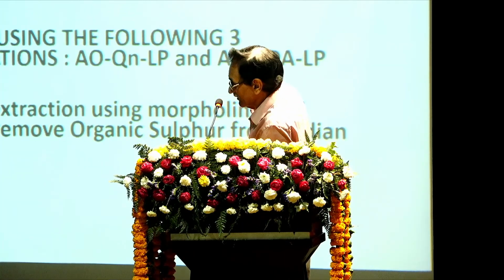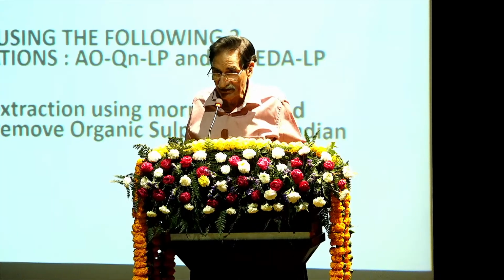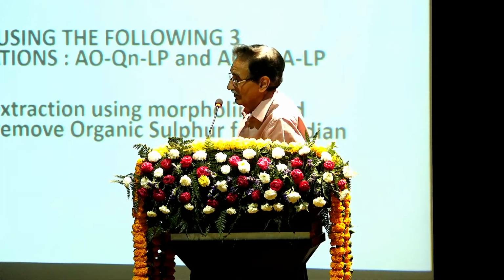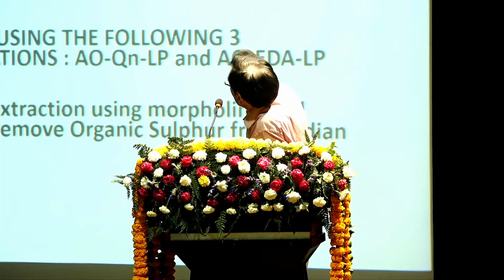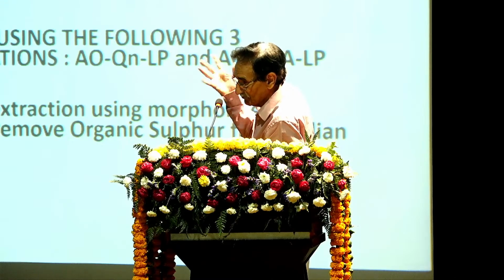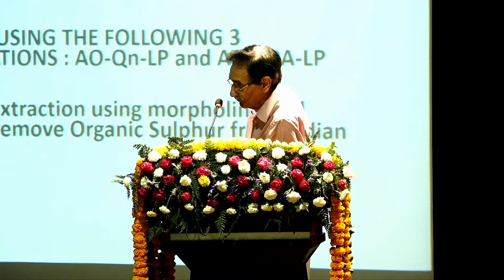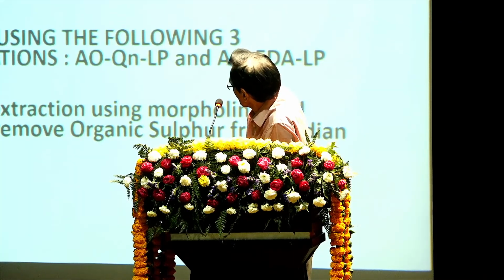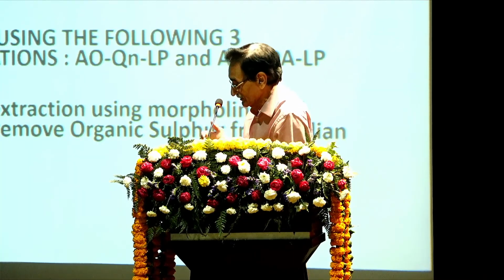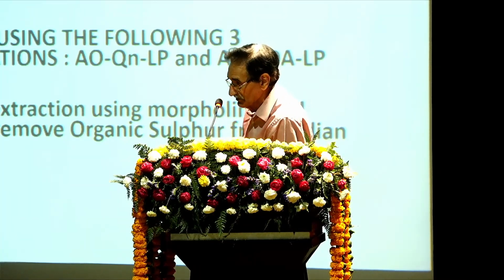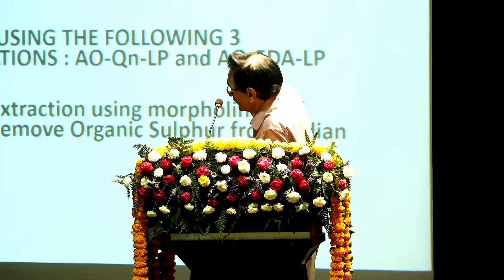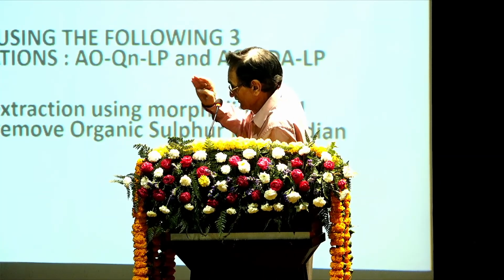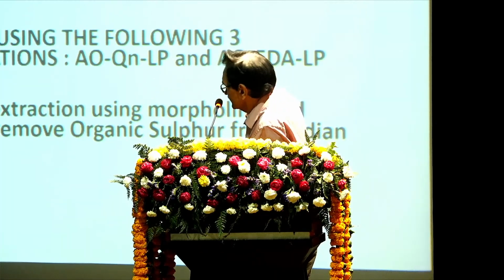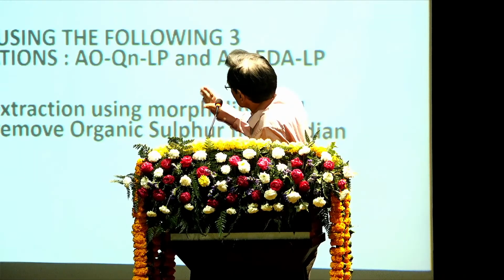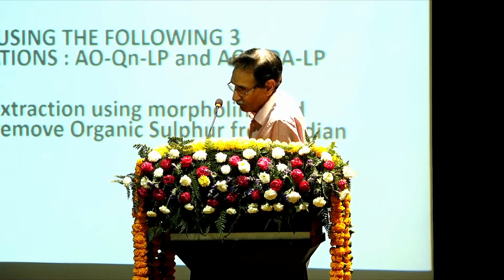That was not an easy task, because the extractability of coal in common organic solvents listed here, DMSO, chloroform, benzene, heptane, etc., is not more than 15 to 20%. That much solubility will not do, so we thought of using different techniques. We thought of using coal-derived chemicals to cut down the cost. We used anthracene oil, quinoline, and liquid paraffin in succession, stepwise extraction, and then anthracene oil, ethylene diamine, and liquid paraffin through successive extraction techniques. And we were able to get 50% coal extract.